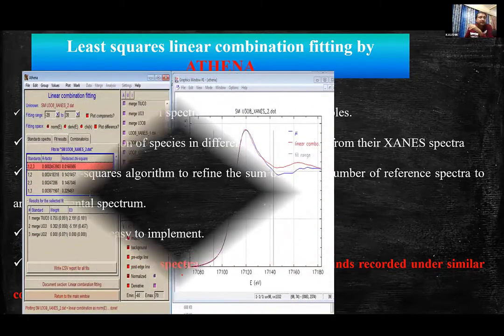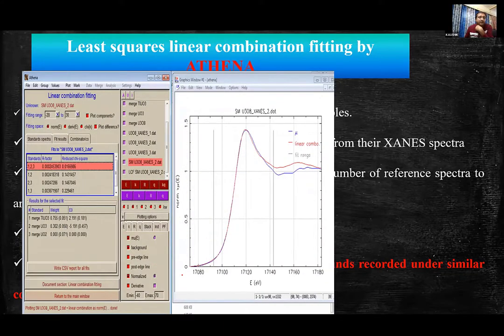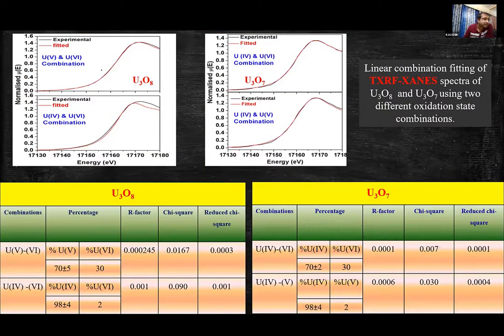So you can see that this is the interface of the Athena software. The red color is the fitted linear combination spectra, and this blue color is the actual spectra. So in case of U3O8, as you can see, we have tried both combinations. We have tried both uranium 4-6 combination as well as uranium 5-6 combination, and this red color is basically the fitted spectra. So you can see that if we take the combination of uranium +4 and +6, the spectra do not fit well. However, if we take the combination of +5 and +6, it is much better fitted.